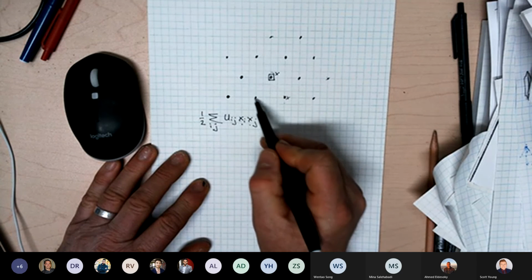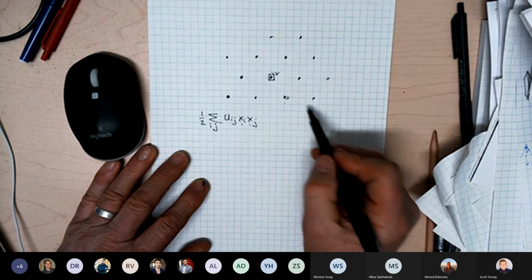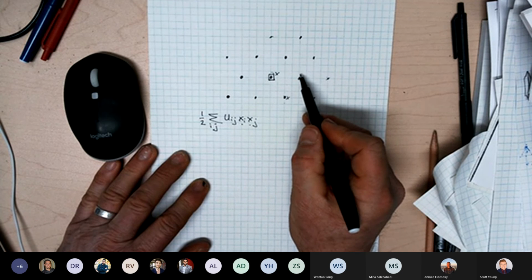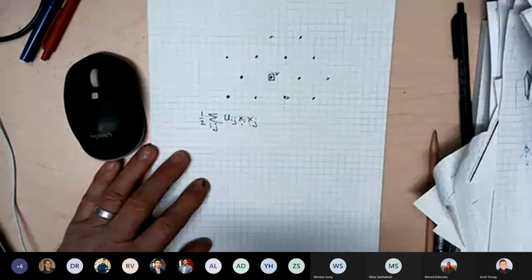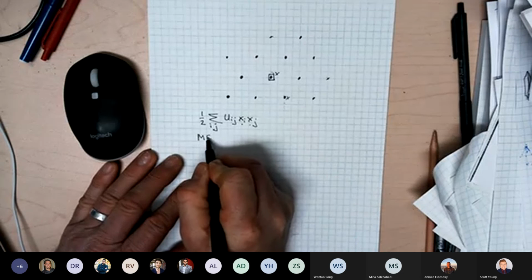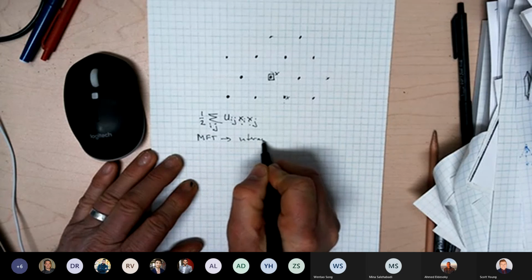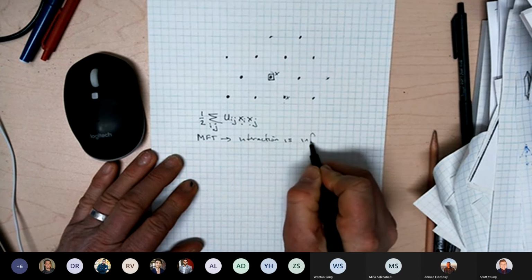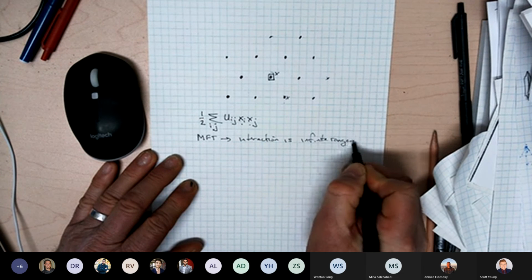We just say there's 6 near neighbors, but whether they're full or empty, we can't tell, because we're just saying everything is equal to the average. So what we're basically saying in mean field theory is the interaction is infinite ranged.